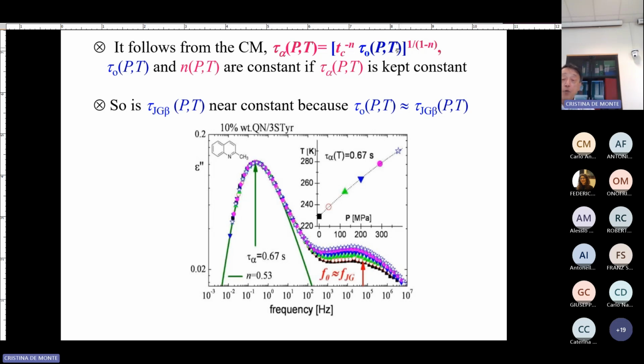So this equation here already guarantees you that not only is the shape constant, but also this relation between tau 0 and tau alpha is the same. If you keep this the same, because this n doesn't change, the shape doesn't change, meaning that the Kohlrausch exponent 1 minus n doesn't change. So this is a constant. N doesn't change. 1 minus n doesn't change. So that means these two have to be kept the same.